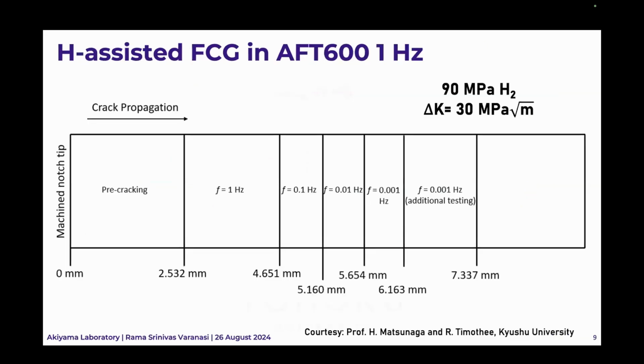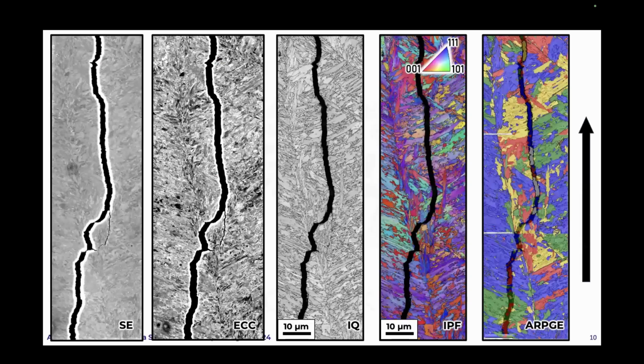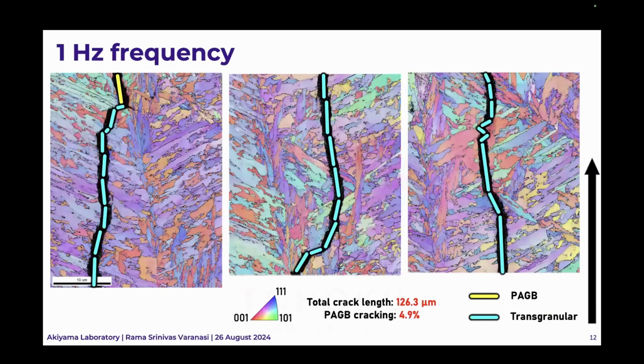However, we have samples from Professor Matsunaga's group after performing these CT specimens in 90 megapascal hydrogen. And when we look at a frequency of 1 Hertz, what we observed was something very interesting. This is the prior austenite grain boundary, and this is the fatigue crack growth. And when we observe a total crack length of about 126 microns, only 5% of this total fatigue crack growth was along the prior austenite grain boundary. So this is predominantly transgranular.